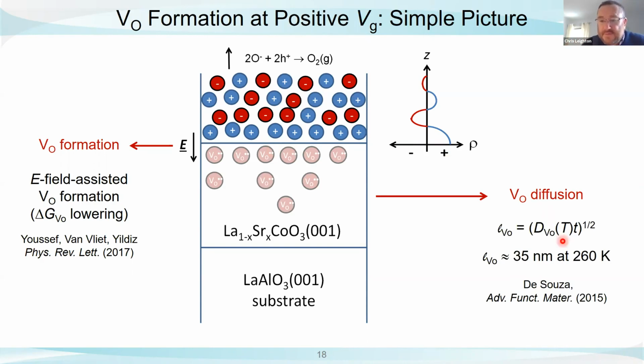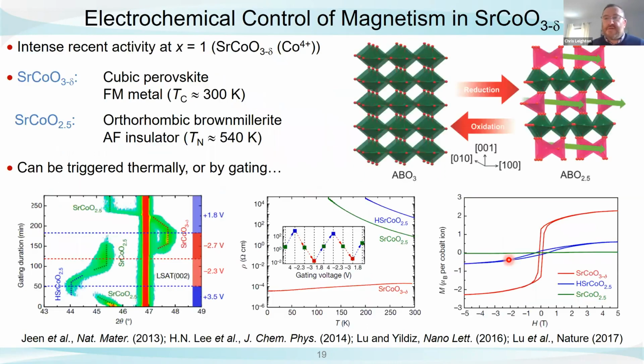Even underneath room temperature, here at 260 Kelvin, with the known diffusion coefficients that have been measured in this material, the diffusion length for oxygen vacancies is safely thicker than the film. If we work at something like 300 Kelvin, it's actually many times the thickness of the film. So it's no mystery that we're able to do this. We're able to do this because the materials are very, very good oxygen transporters. So this has really put a spotlight on the cobaltites in the literature on this topic.